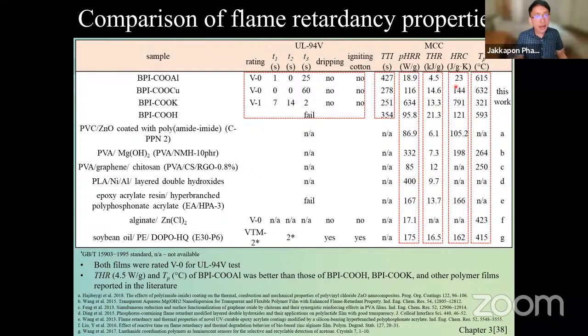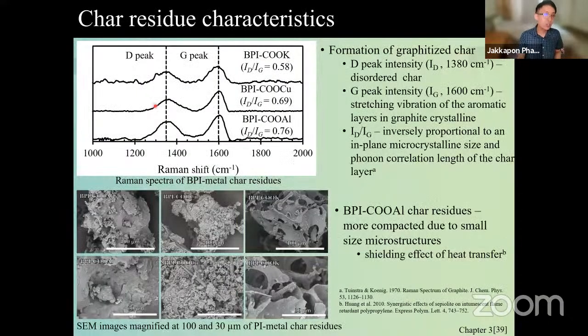Now we always study chemistry, right? We want to know why this is good and why these are not so good, the copper one, the potassium one, and all these. And there is a way to study that. So we study Raman shift. We're going to look at its peaks, see the D and G peaks and take the ratio of them. The higher the ratio, the more graphite char there is. If it's a higher ratio, it means that there are smaller microcrystallite sizes. That means that the burning is very slow. And we can look at this in the SEM as well. You see that aluminum has very small particles there.